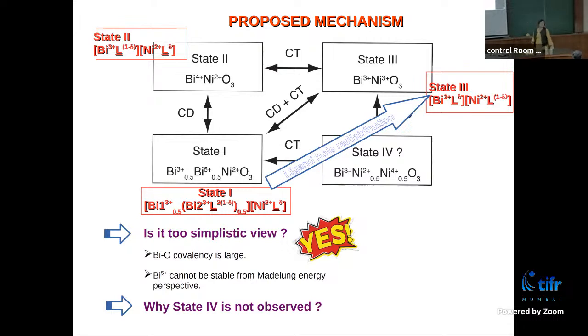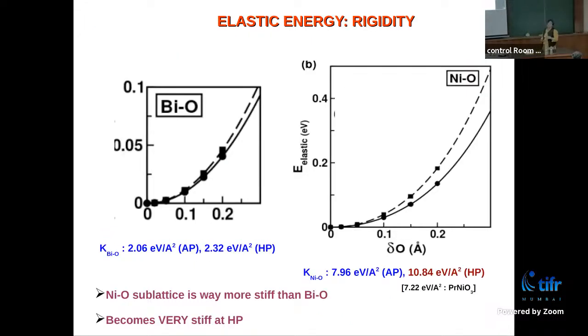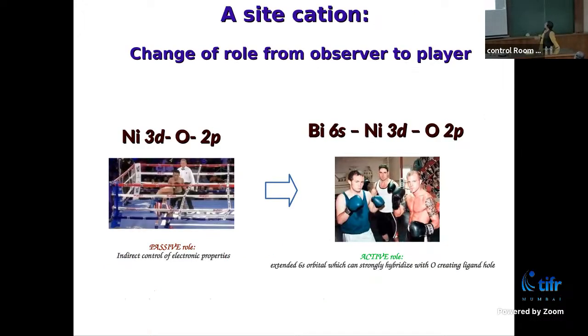Now, why is the state 4 not observed, why didn't they see the charge disproportionation at the nickel side? The only answer to it is we calculated the stiffness of the lattice, and at this high pressure phase, the stiffness of the lattice is way more than what it needs to allow this bond length being short and long, short and long. And so this is a picture.